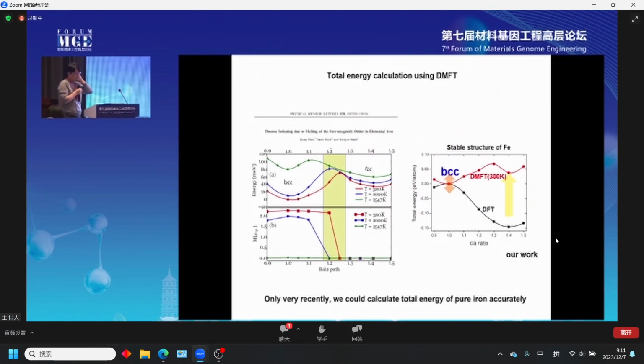Okay, let me start from the shortcoming of DFT. Maybe you know that DFT has a very big problem describing the ground state of transition metals. Density functional theory cannot predict the BCC to FCC phase transition of iron, which has partially occupied d states. But only very recently, dynamical mean field theory, which can describe many-body effects, can explain this BCC transition. In 2018, Kristjan Haule at Rutgers University for the first time succeeded in calculating the total energy of the BCC to FCC phase transition at finite temperature using dynamical mean field theory, and we successfully reproduced their data.